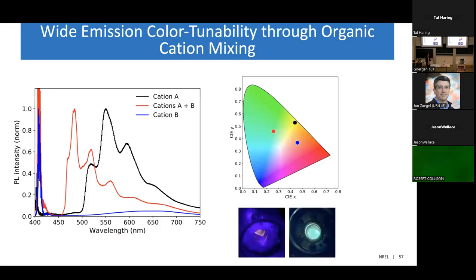Now, when I plot the spectra associated with these 3 compounds together, you can see just how different they are. All right, so we have the pure naphthalene system, which is the spectra in black, the pure hexylammonium system, which is the curve in blue, and then the mixed one is the red curve. And the color coordinates associated with each of these spectra vary anywhere from green to yellow to orange, depending on the organic composition. And you can also see some photographs down here for the orange and the green emitting films.